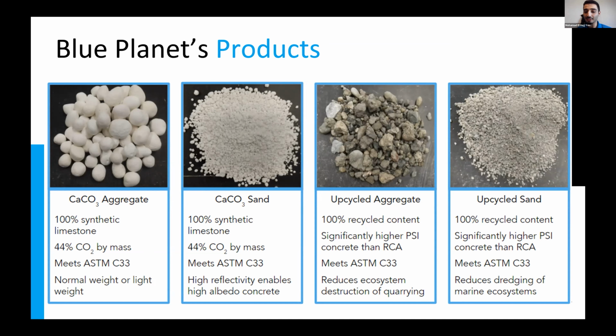But the upcycled aggregate in itself is significant because it's recycled material. In comparison to RCA, you can use more of this upcycled material. RCA is just recycled concrete aggregate. You can replace more virgin aggregate with this upcycled aggregate in comparison to recycled concrete aggregate. Both of these products meet ASTM C33, which is a standard for aggregate, and both really promote minimal environmental degradation. Here in California, we have material shipped from Canada and from Mexico. So rather than having to ship that material over many miles of ocean, we're providing this to local projects, and it's coming from the demolition of local projects as well.